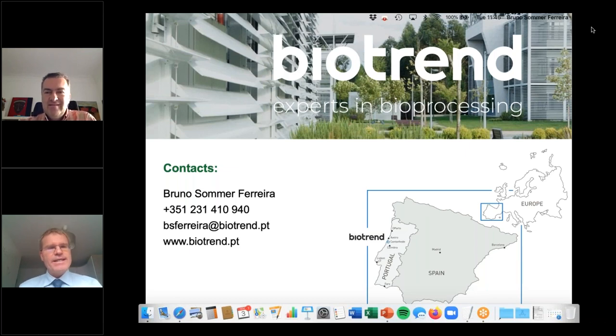Exactly. Okay. So yes and no. We produced biofilms out of it. We obtained the PHA extracted by Biotrend, and we made biofilms with a hot press to characterize the biomaterials a little bit. So that's not 100% comparable with an extrusion process, but to get some characteristics for the biofilm, this is already a good indication. And the colors, as Bruno showed in some pictures, if it's properly extracted, then it will be white or more or less white.